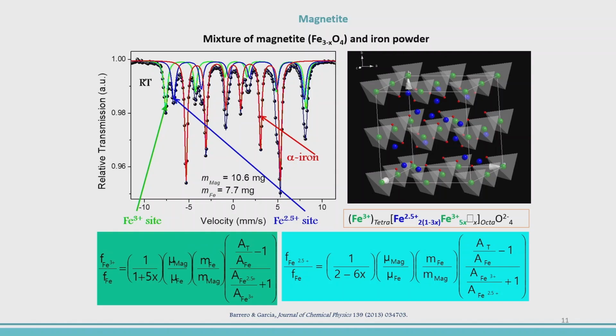We can say, no, there are vacancies in the tetrahedral. No, this is not correct. So this is just to show how it works if we propose this formula here. So the X value has to be determined independently with another method. There are many methods to determine X. So after using the previous equation, taking into consideration the distribution of the irons in both sides, tetrahedral and octahedral, then we get these 2 equations.